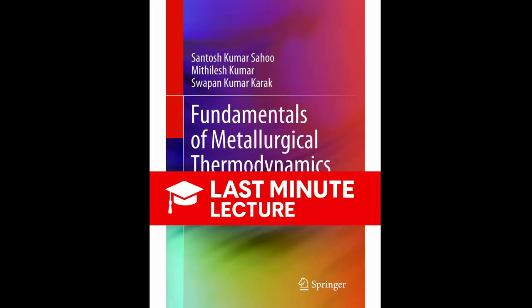Similarly, section 4.11 covers Trouton's rule for vaporization. This rule states that the entropy of vaporization, delta S vap, is approximately constant for many substances boiling at 1 atmosphere, with a value commonly cited as 87.864 joules per Kelvin mole. This one is even more robust than Richard's rule. If you know the normal boiling point of a metal, you can get a really accurate estimate of its heat of vaporization. These empirical rules just underscore the inherent similarity in how materials transition between phases.